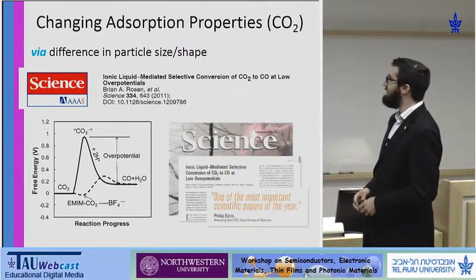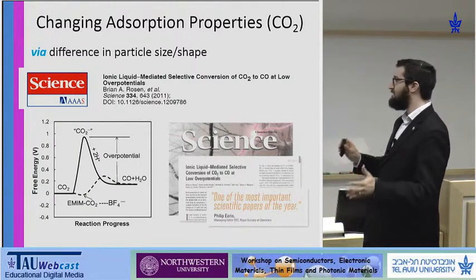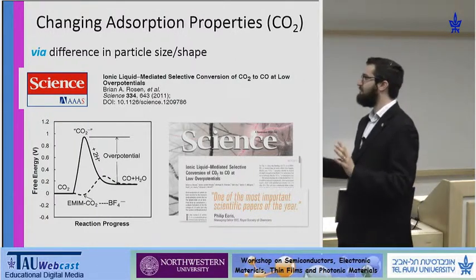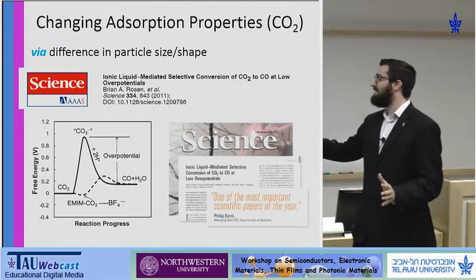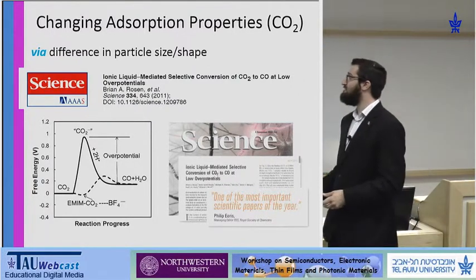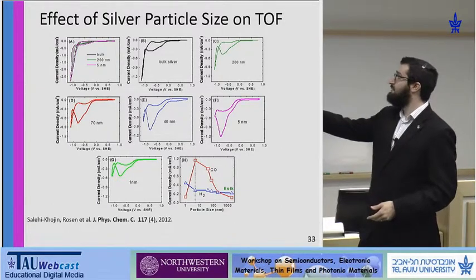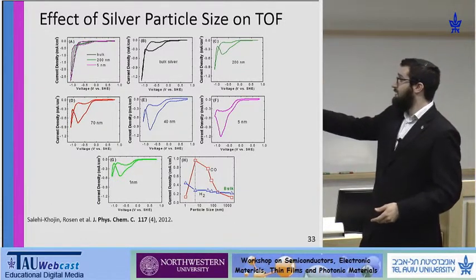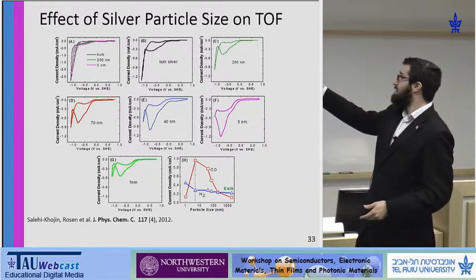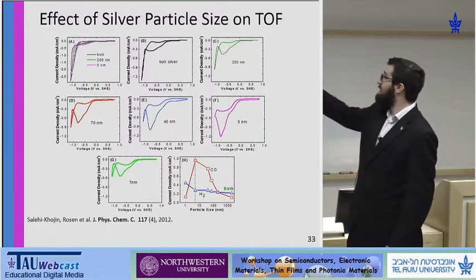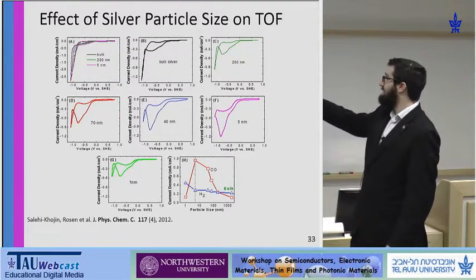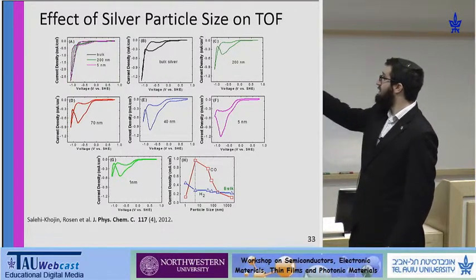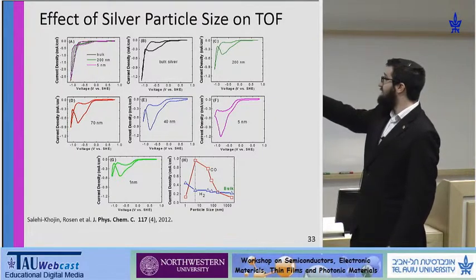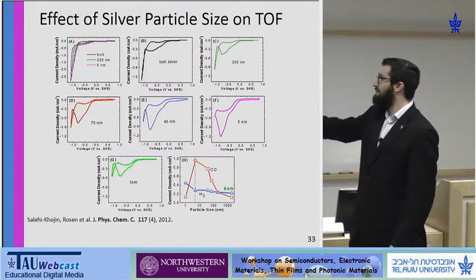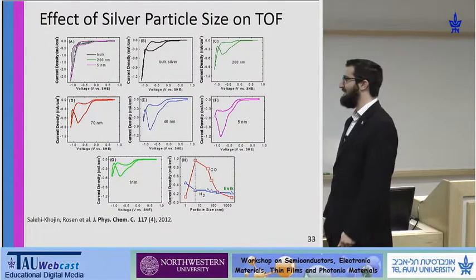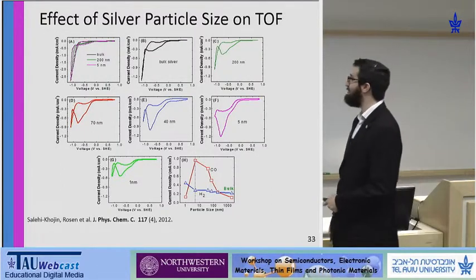We've employed a similar technique during my PhD, where we changed particle size using an ionic liquid electrolyte in order to convert carbon dioxide into carbon monoxide. And by changing the crystallography via the particle size, we see what is most likely a volcano plot, increasing current of carbon dioxide reduction as we decrease the nanoparticle size down to 5 nanometers. Then once we hit 1 nanometer, we see a decrease in activity again, like the volcano plot I showed you at the beginning of this presentation.